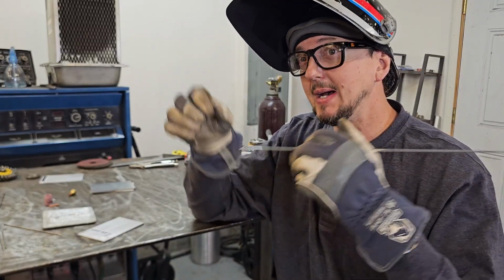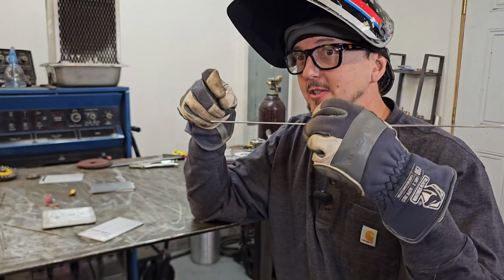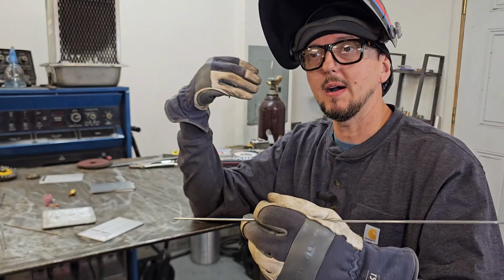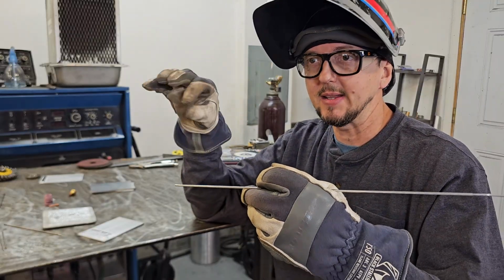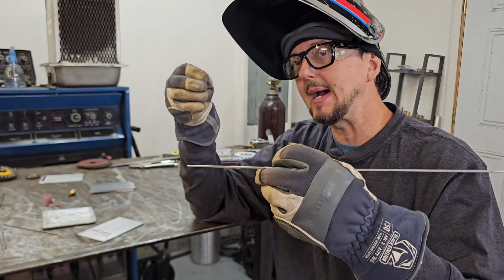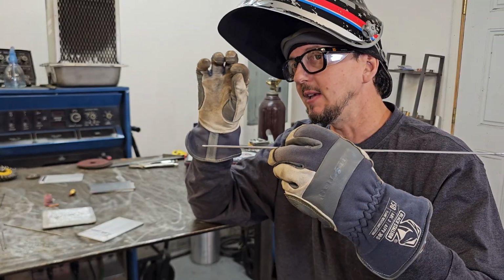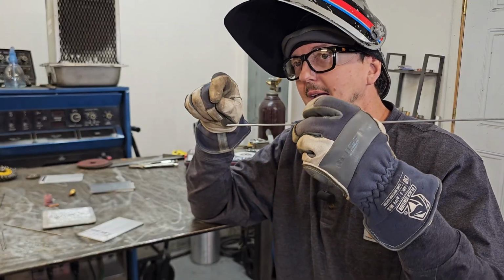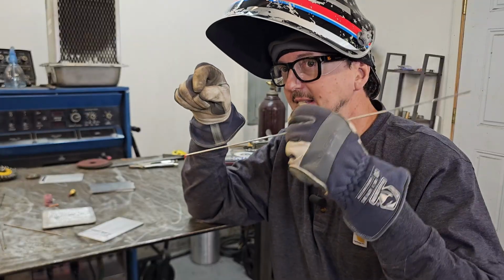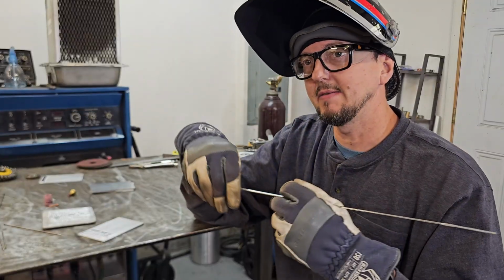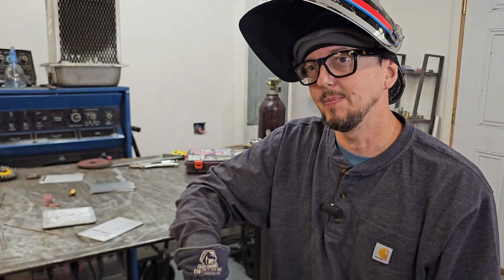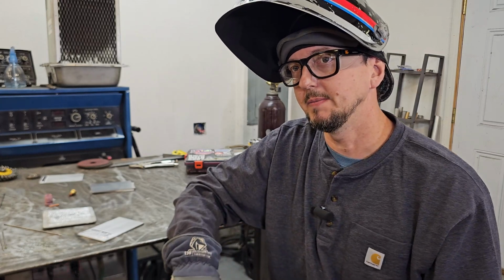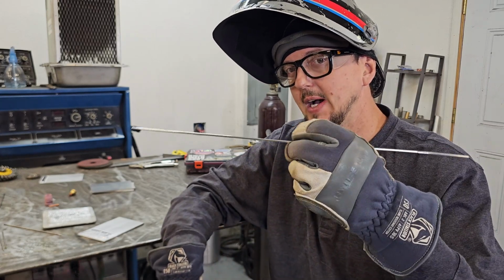If you get stopped up and you don't know what to do, you're having trouble getting enough through, back way off that pedal, not so that the arc extinguishes, but back almost all the way up so that you just have a very small arc, and then get more in your fingers and then continue to dip. And you can do that several times throughout the weld until you feel more comfortable, okay? So that's advancing filler rod through your fingers.